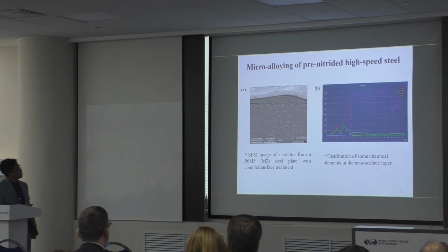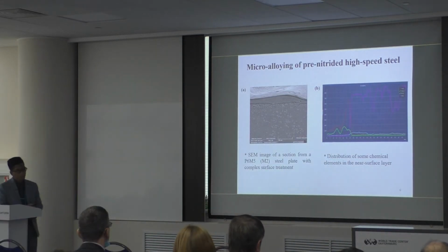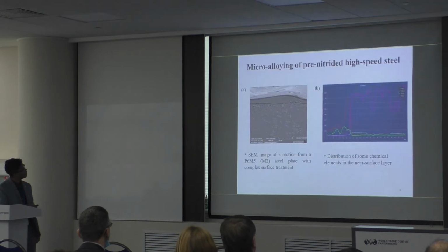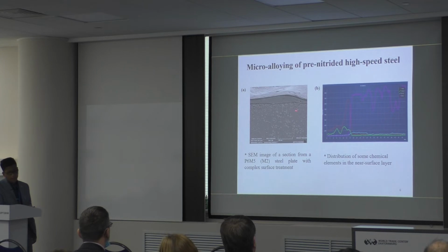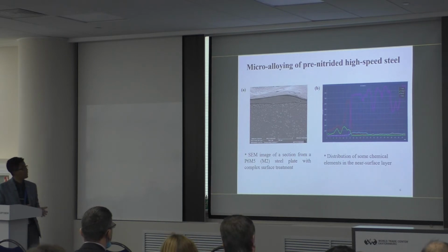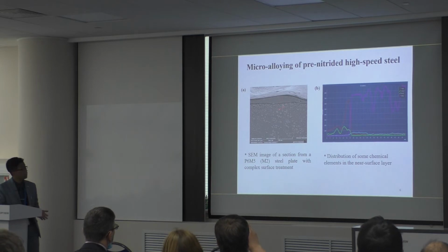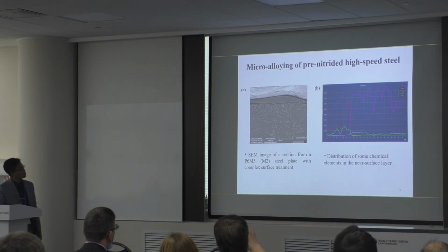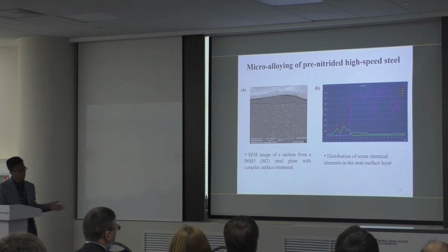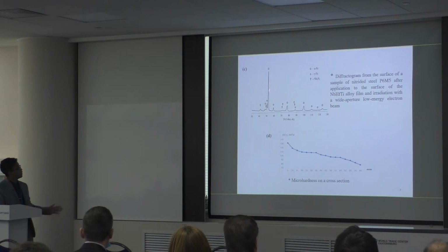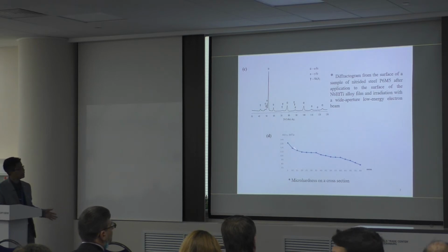The slide shows the microstructure of nitrided high-speed steel. Figure A, the outer layer of the blade was enriched with refractory nitride phase. The depth of the near-surface layer in which the modified structure was obtained is up to 10 micron. Figure B, distribution of chemical elements in the near-surface layer. Figure C, diffractogram. Figure D, the distribution of hardness by depth showed that it increased to a depth of 80 micron.